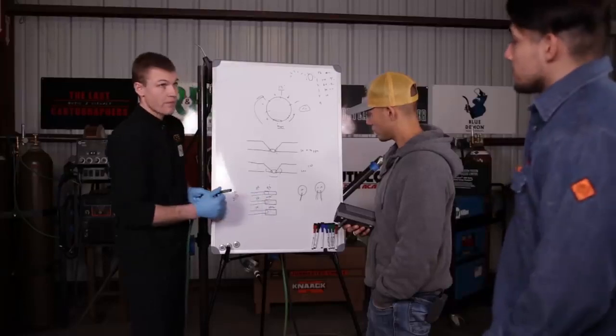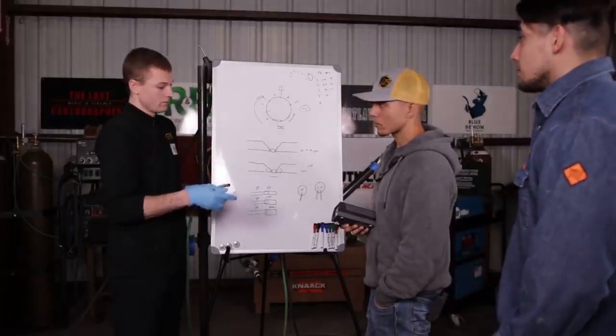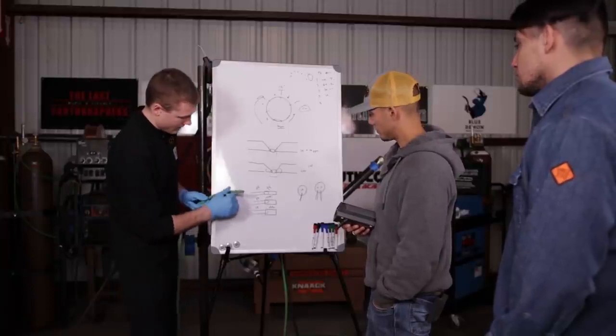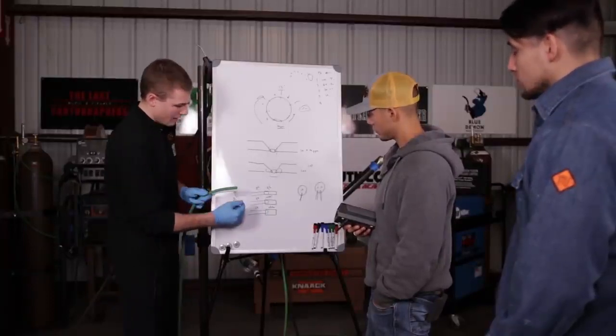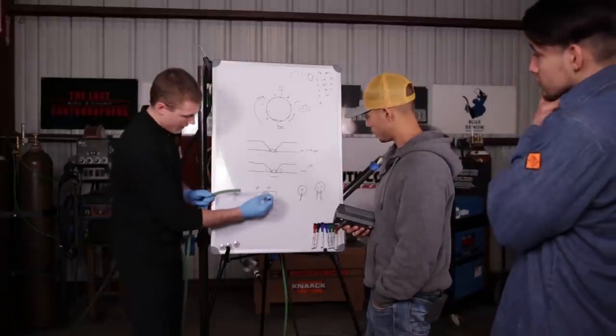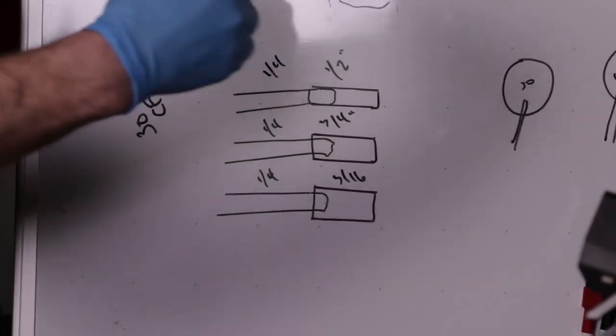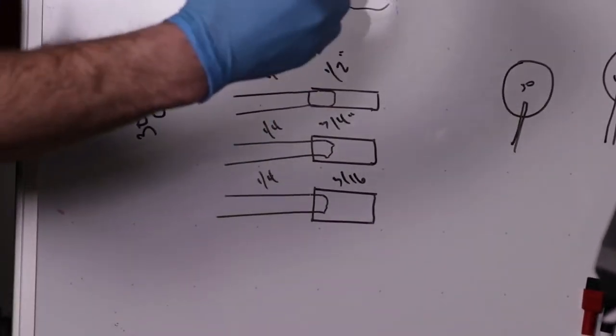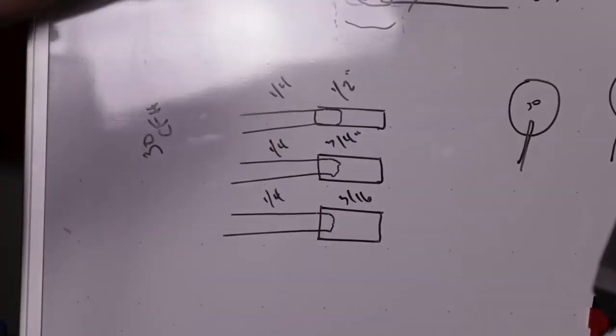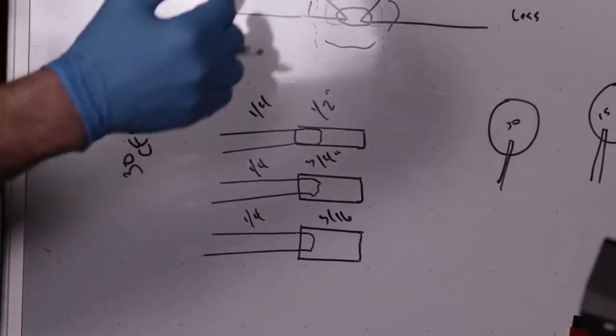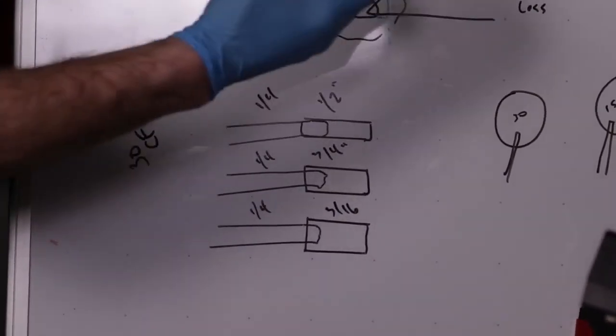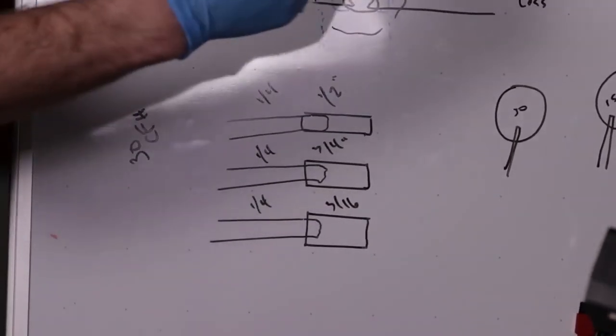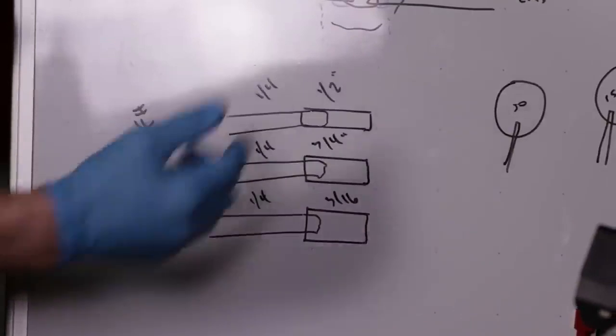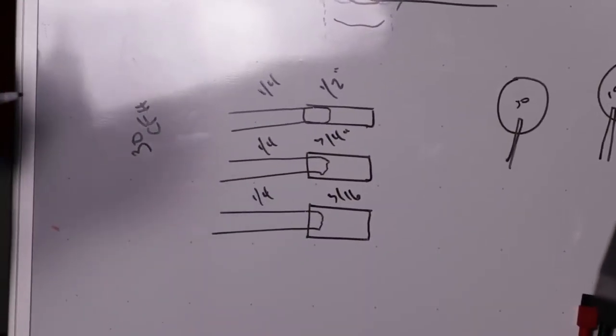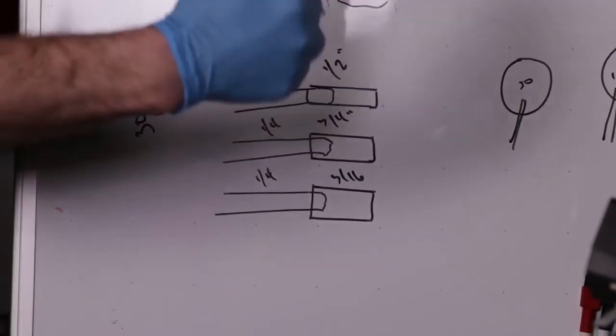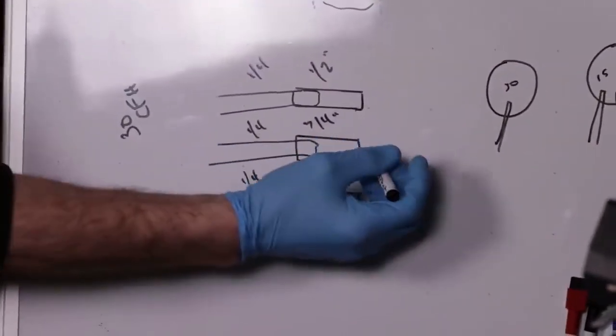Now, the bigger the pipe, the bigger the diameter you want the hose to be? Within reason, but I'll get to that in a second. So if we have a 1/4 inch hose, you could take a 1 foot length of larger ID hose, slide it over, and tape the end off, and now you have the same 30 CFH flowing out of a larger pigtail, so the turbulence will be a lot less. A 1/4 inch hose with a 3/4 inch ID pigtail, 1 foot length, taped on, and the turbulence will be even less.